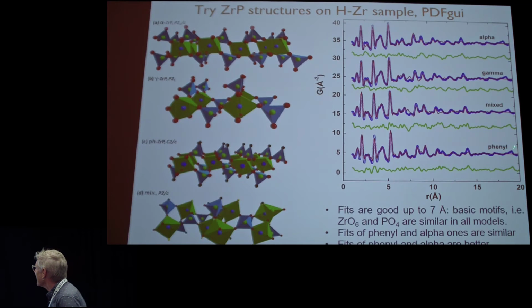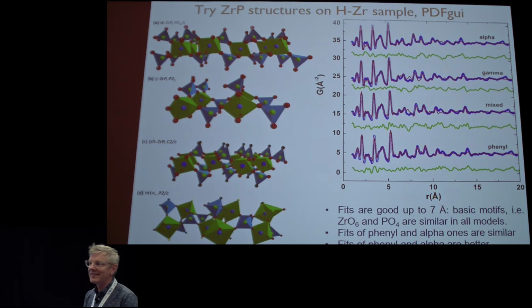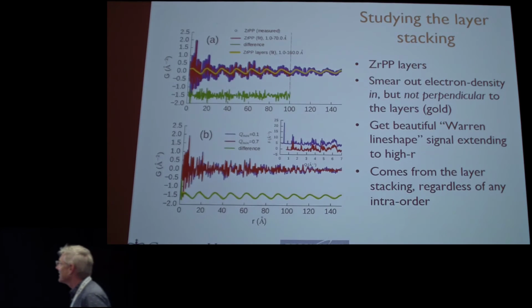And he figured out that it was this one called phenyl, which I can't remember which one it is. But anyway, we're differentiating between competing models to get the layer thing. But there's even more information about the morphology. If we take the PDF that we obtained from this material and we smear out the electron density in the metal layer, we get this smooth yellow line. So Max did this, and you see this beautiful zigzag line.